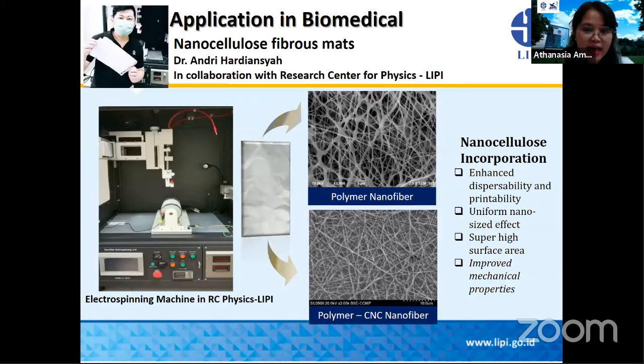This is our initial research result, in collaboration with the Center for Physics in LIPI with Dr. Andri. We can see here that the introduction of cellulose nanocrystals significantly changed the morphology of the polymer into a very small and uniform nano-size. This definitely can enhance the super high surface area, as well as improve the mechanical properties, which is really beneficial for biological applications.